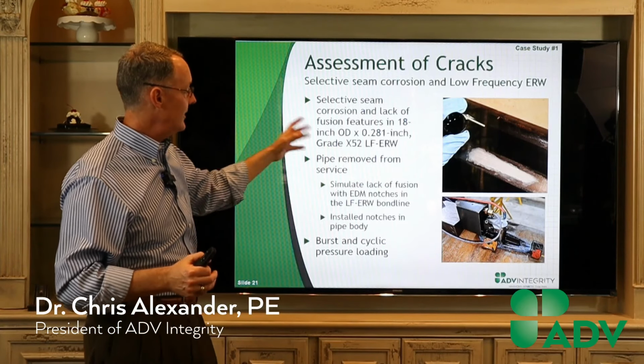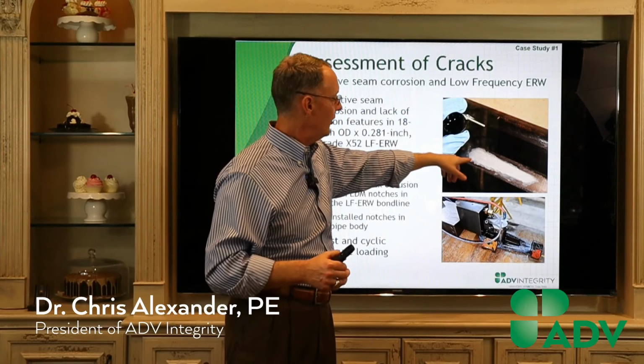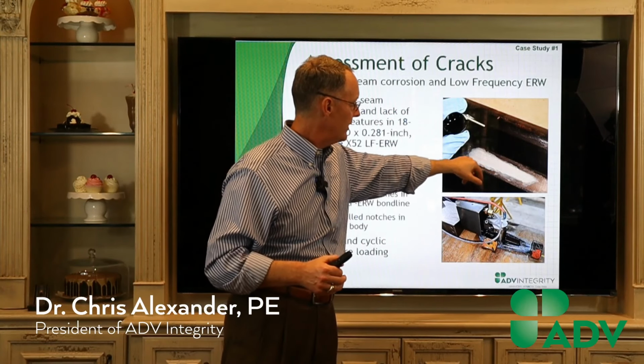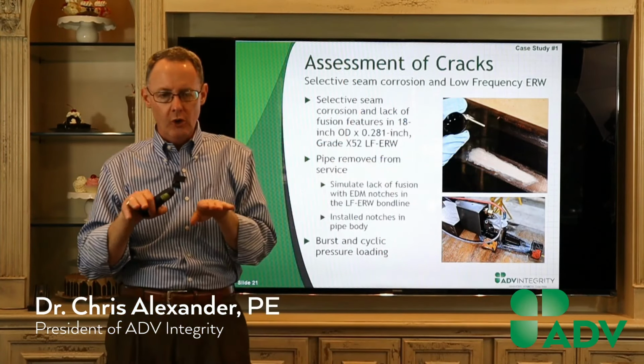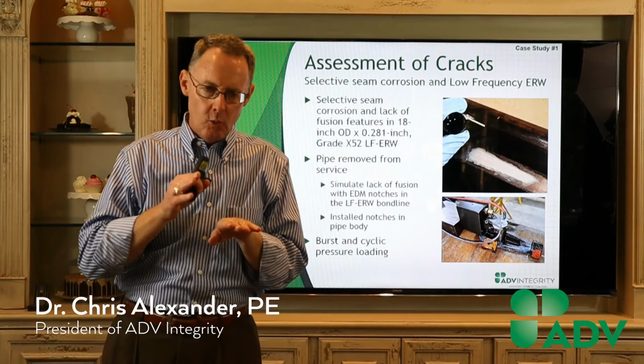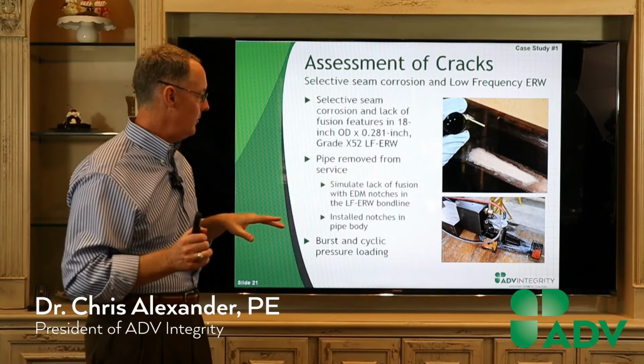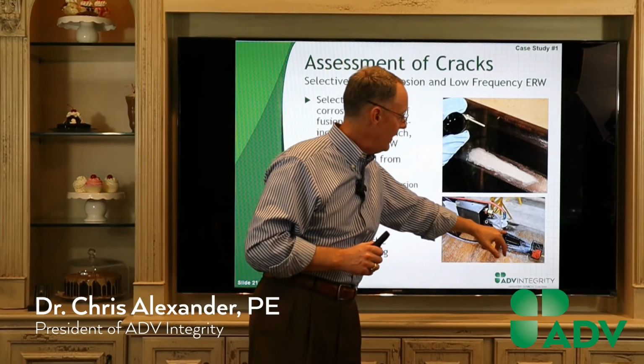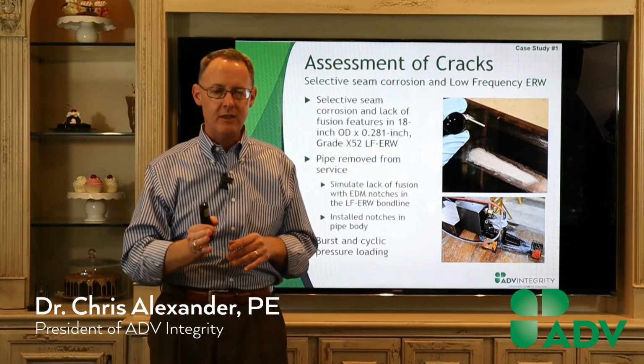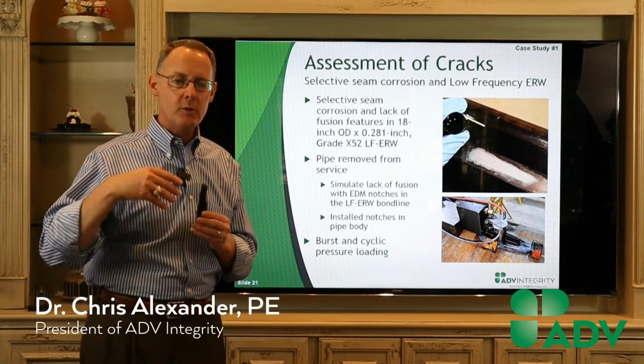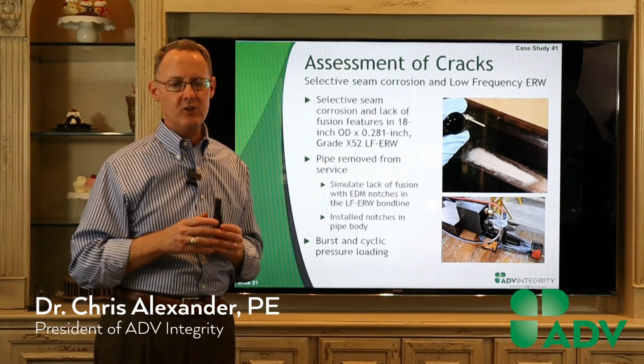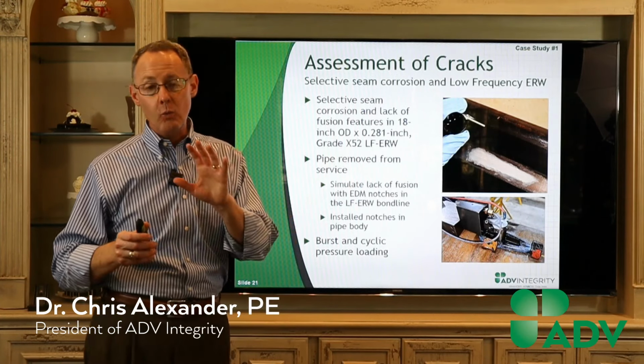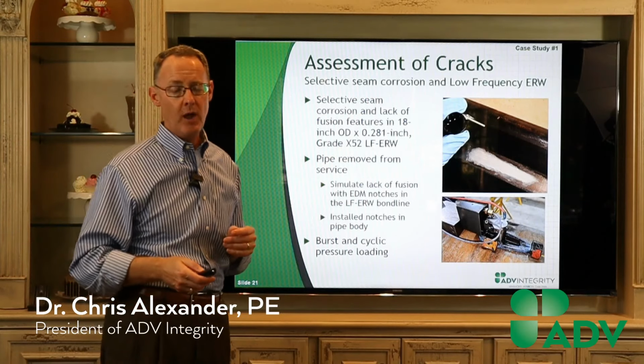The way it starts, if you're looking at low frequency ERW, is you take a piece of pipe and you etch that surface and you're looking for that bond line. Once you find that bond line, then you put an EDM notch, and this is a little machine that illustrates putting an EDM notch into that seam, and then you do some pressure cycling. So this case study walks you through the process that we do to create cracks in pipe.